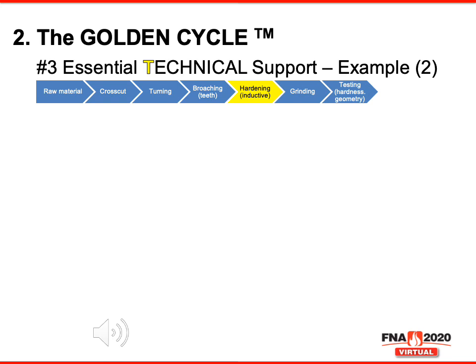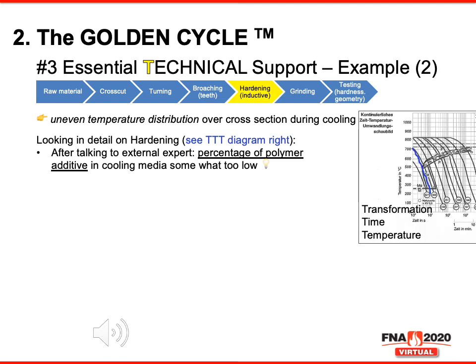Now we look in detail at the hardening process, how an uneven temperature distribution over the cross-section during cooling could happen. We took a look at the so-called TTT or time-temperature-transformation diagram, and there I found that for this specific material the percentage of polymer additive in the cooling media was somewhat too low. If it's too low, then the cooling is too strong and it could cause stress and cracks in the material.